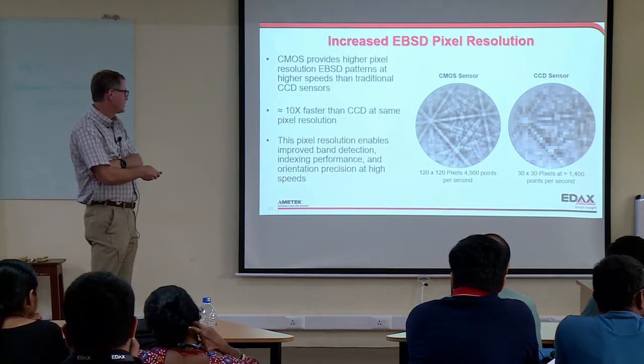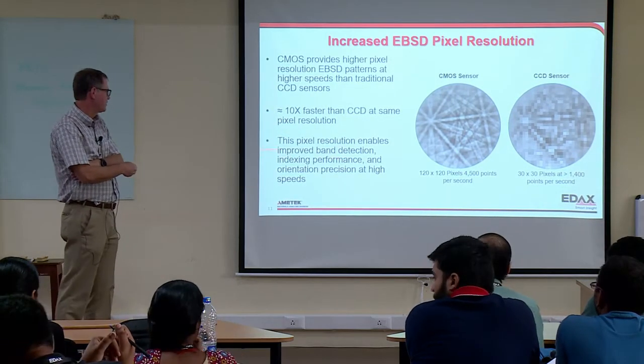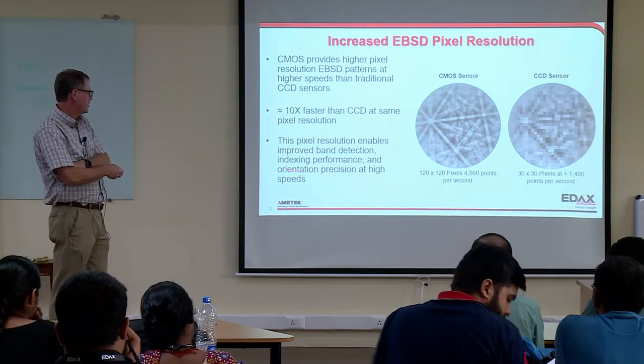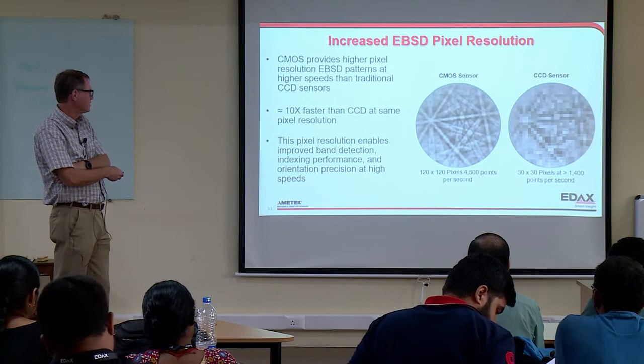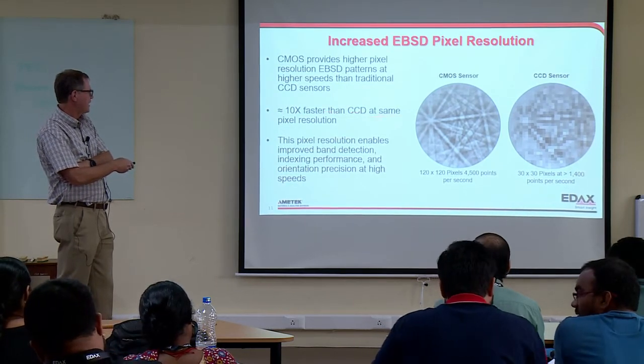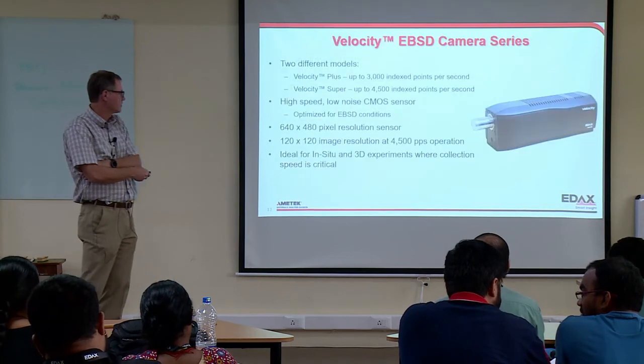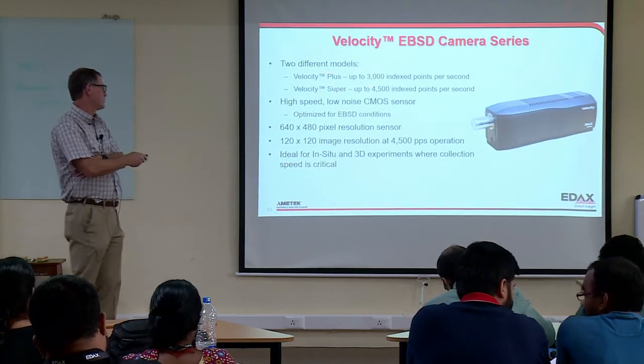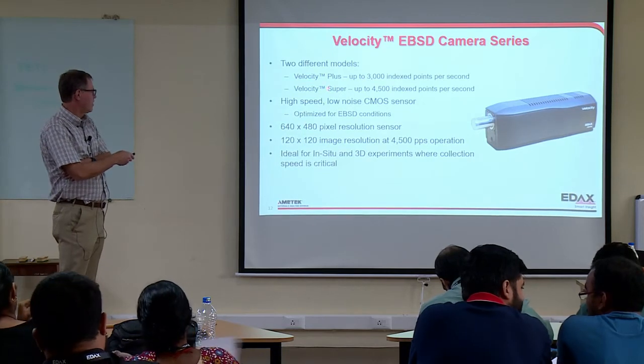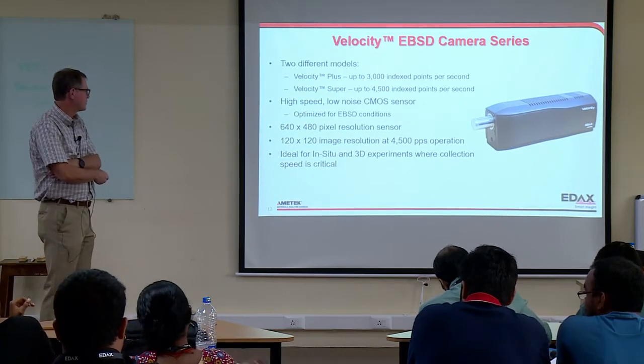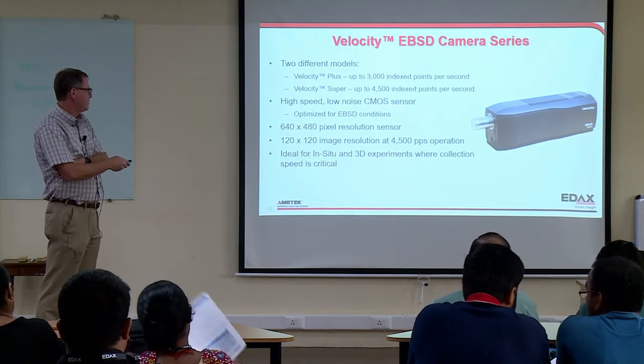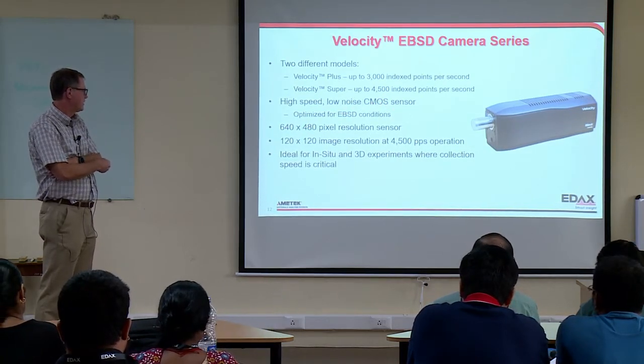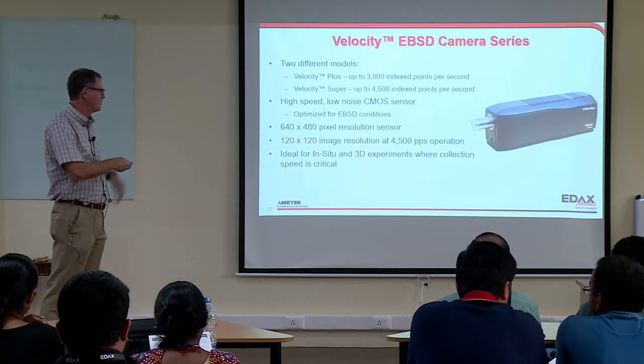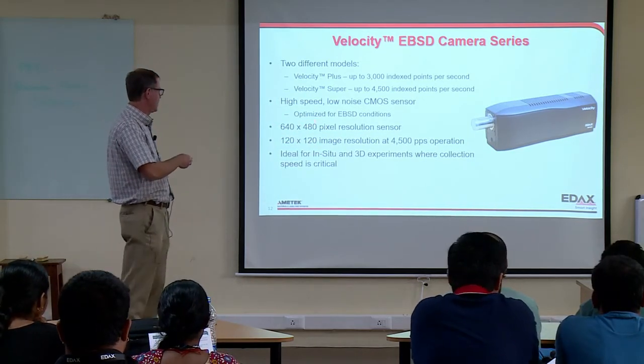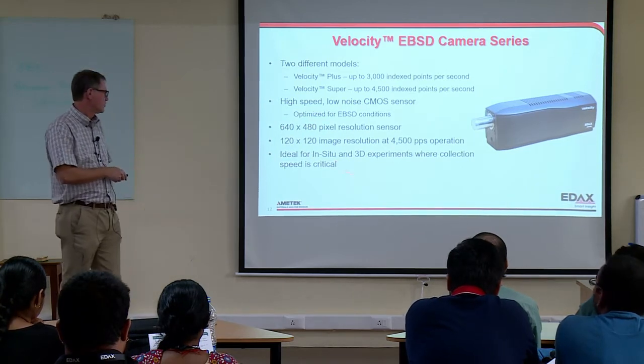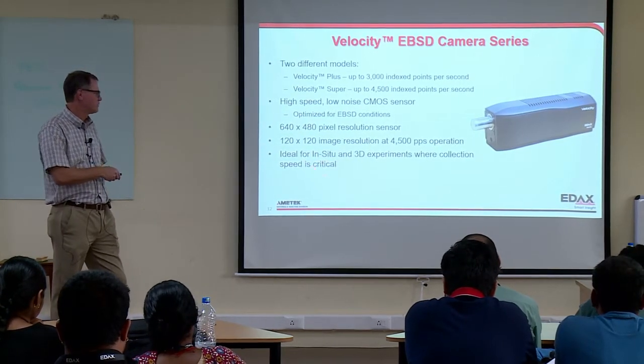So that increased pixel resolution does help some things. It can help us with improved band detection and especially with orientation precision at fairly high speeds. It's 10 times faster than the CCD at the same pixel resolution. Like I mentioned, there are different models of it, and the Super goes up to 4,500 points per second. It's a high-speed, low-noise CMOS sensor, and we've optimized it for EBSD conditions. It's actually 640 by 480, but we only use a square part of it. So it's really ideal for situations where speed is critical.